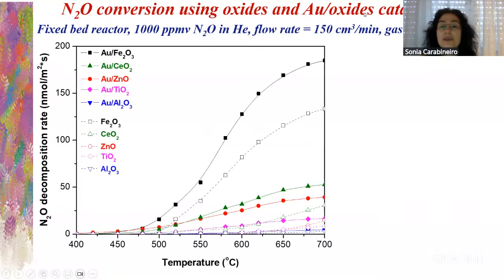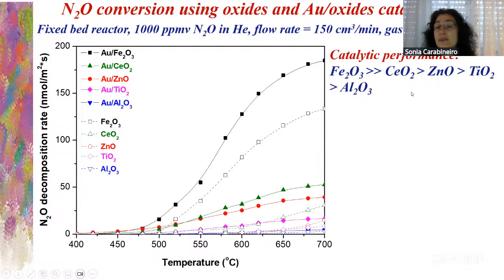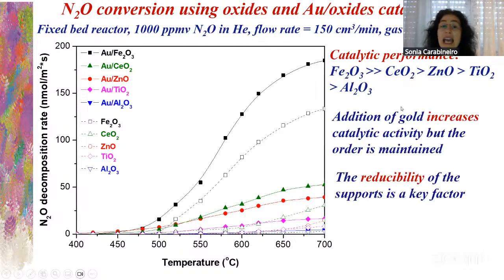The reduction is facilitated. So we have here N2O conversion using oxides and gold on oxide. What we see here is that the catalytic performance follows the reduction capacity, shall we say. So iron oxide is better than cerium oxide, better than zinc, than titanium, than aluminum. And the addition of gold increases the catalytic activity, but this order is maintained. Which means that the reducibility of the support is playing a very important role. So it's a key factor.